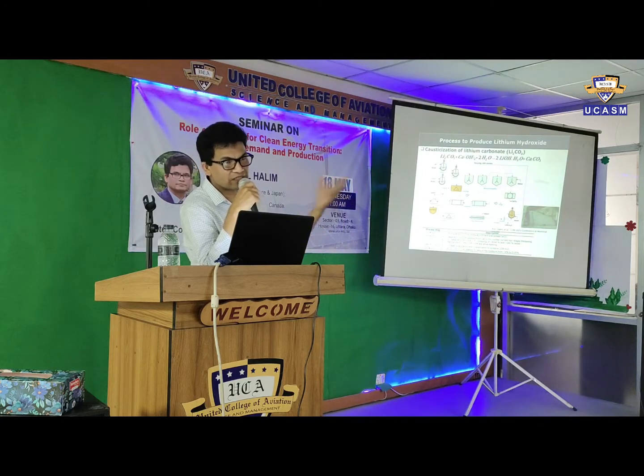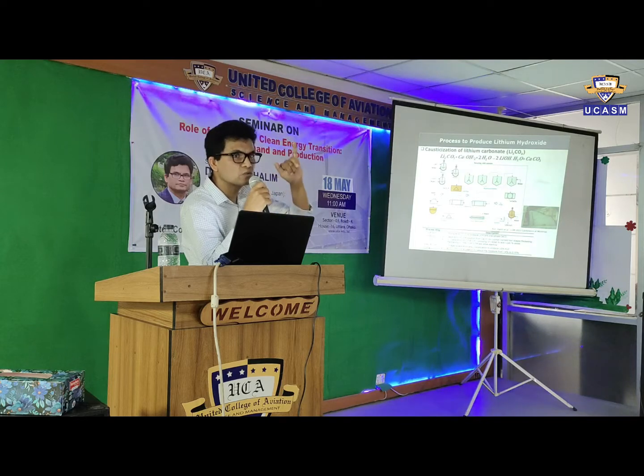Because calcium carbonate absorbs some amount of the lithium hydroxide on the surface. And we are getting a lithium hydroxide product that is in a liquid form and diluted. So to make the lithium hydroxide as a solid, you need to evaporate a significant amount of the water. These are two disadvantages. One, we're losing lots of lithium metal with the calcium carbonate. Second, we are getting very, very diluted lithium hydroxide.